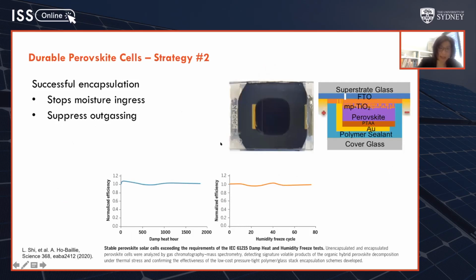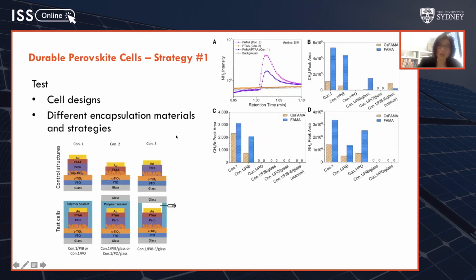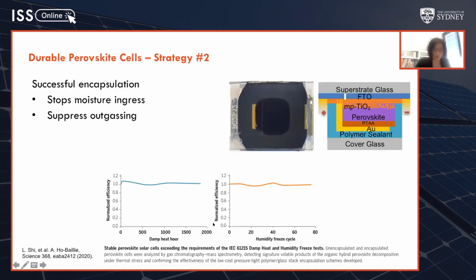And what happens is the encapsulation does two things, and it's important that it does two things. It stops the moisture ingress and it suppresses outgassing. So if there is any void between the cell and the glass, the perovskite has an opportunity to outgas and therefore drives the decomposition reaction. Whereas if the perovskite cell is fully covered in an airtight encapsulation, then it has no chance of having that decomposition reaction proceed. So the cells do really well in three IEC tests: the damp heat, thermal cycling, and humidity freeze. Not only did they meet the requirements, they actually exceeded the requirements.